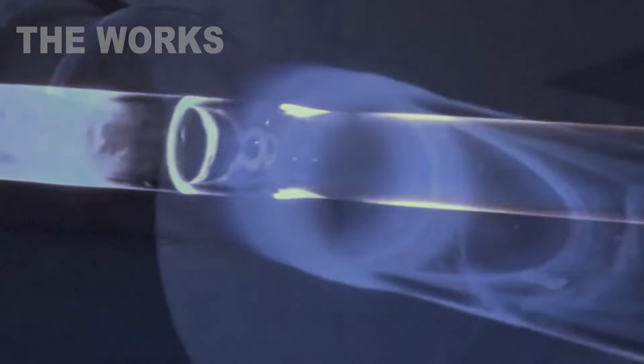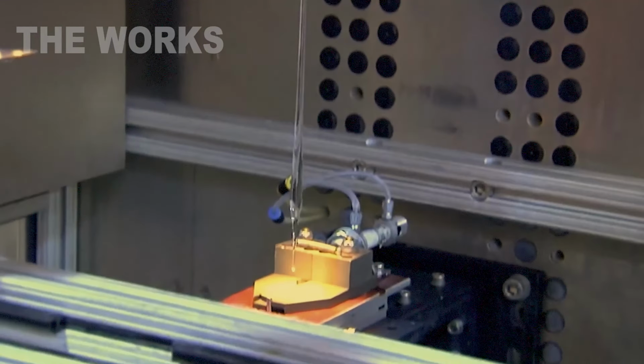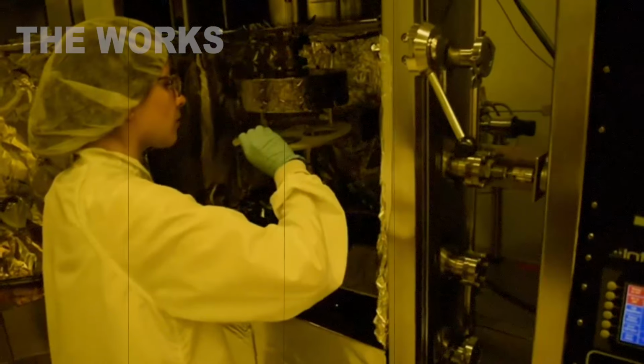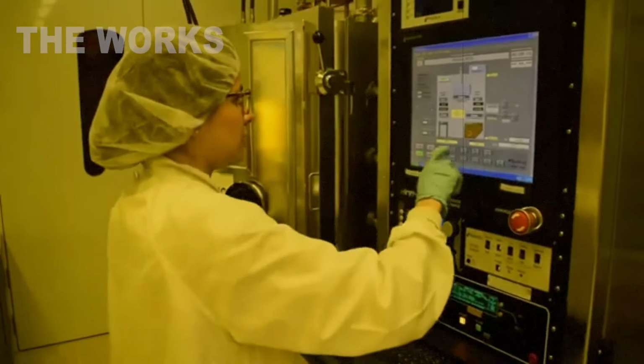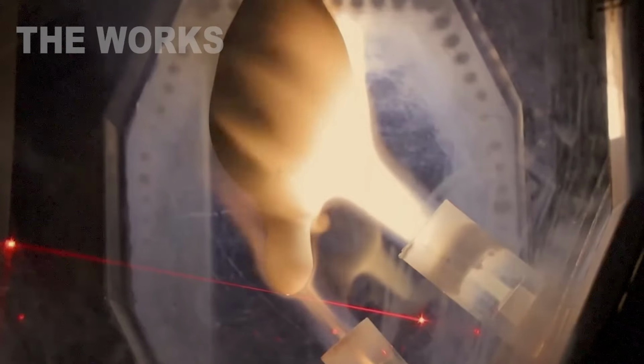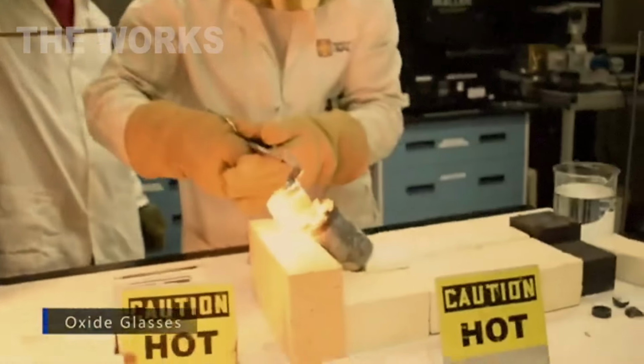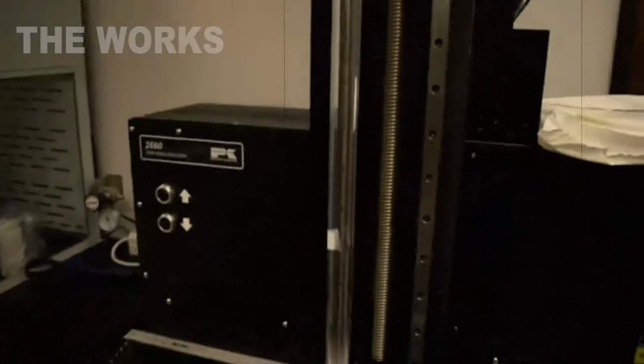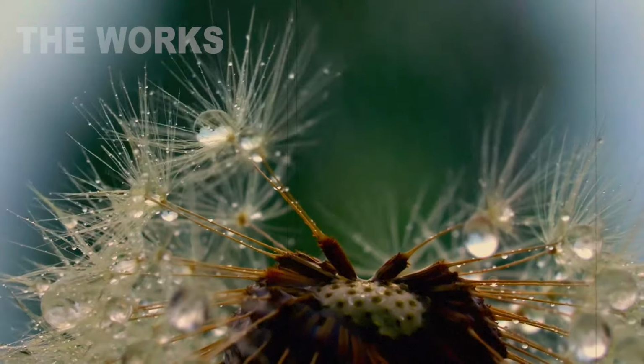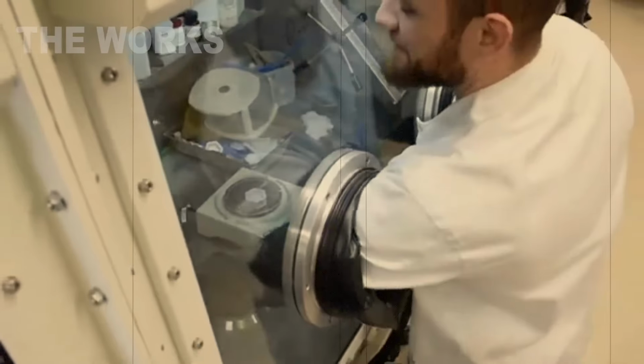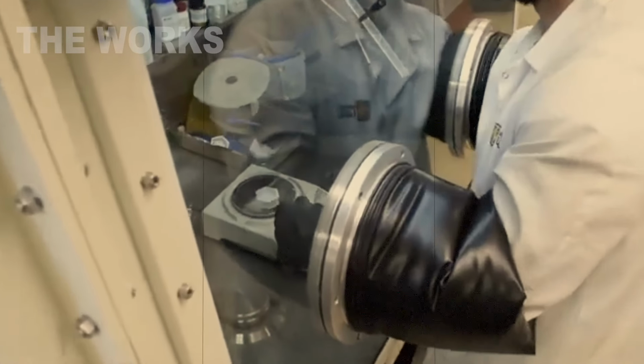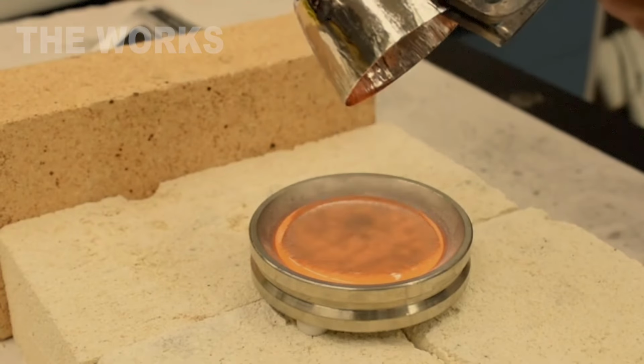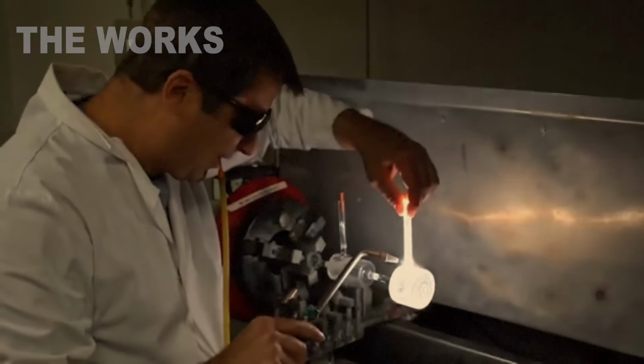A large transparent glass cylinder, which will later be melted and drawn into an extremely thin thread, is the fiber optic preform. This enormous glass blank is made using a method called vapor deposition. In a large furnace, air is mixed with extremely pure gases. These vapors reach the inner surface of a transparent tube that's heated intensely. When the vapors touch the hot wall, they settle and transform into tiny glass droplets, like dew collecting on a leaf in the morning. Gradually, these droplets accumulate layer by layer until a thick layer of glass forms inside the tube. Then this tube is heated even more intensely, and it closes into a dense solid rod. This is our preform.